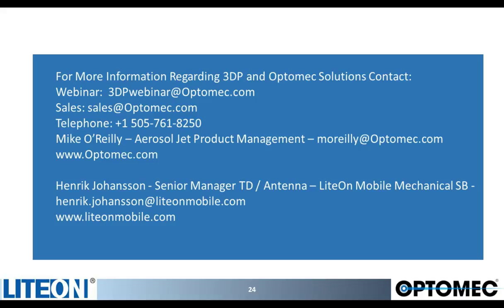Is there any data of electron mobility for metals with respect to curing temperatures? So from Optomec, the answer is we have lots of data. We are just trying to find a material that would work on a low temperature substrate. We work with approximately 20 different suppliers of silver material, probably 120 plus formulations of that material. We tested that material at various temperatures to find out what the resistivity looked like over given periods of time. So we have tons of data relative to that.